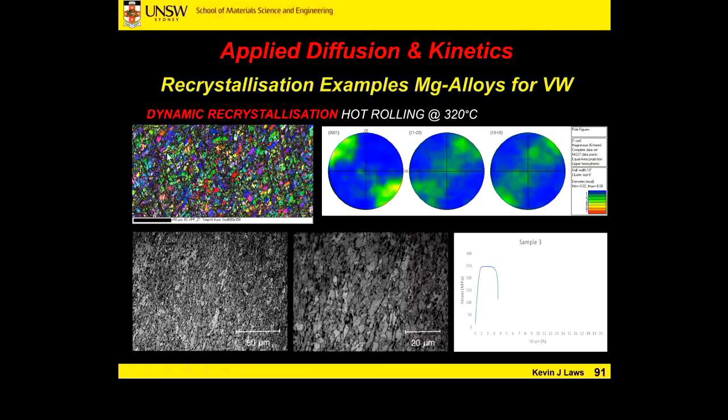Basically, what these diagrams are showing us is a concentration in certain positions on different crystallographic axes, or grain orientations. The majority of the grains we can see in this structure are green or blue. It's not random red, yellow, green, blue. That shows us that the orientation of most of these grains is very similar to one another. They all are lining up.